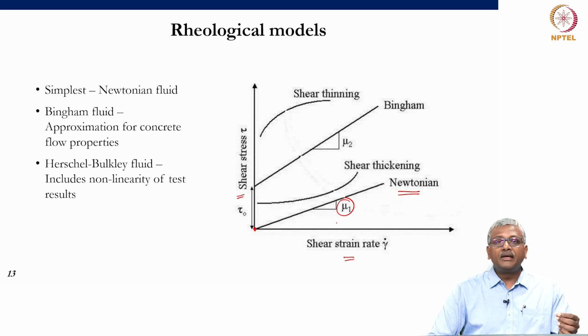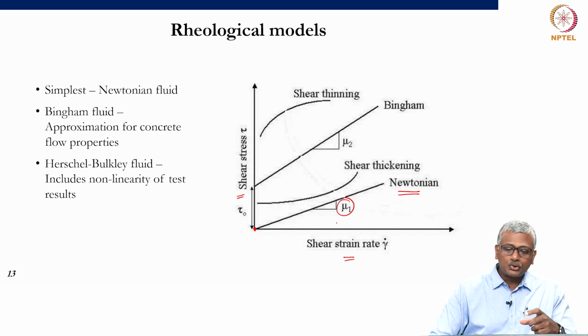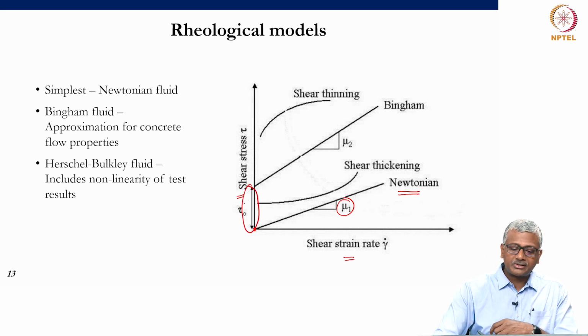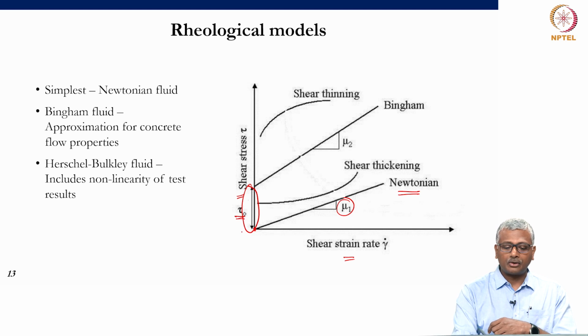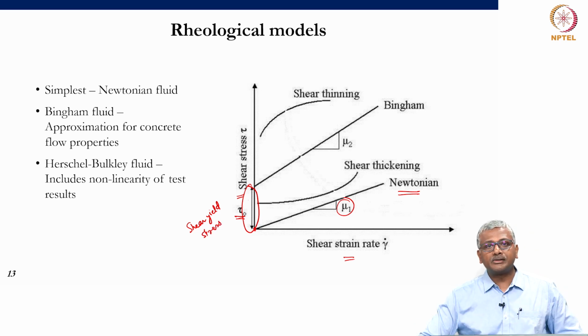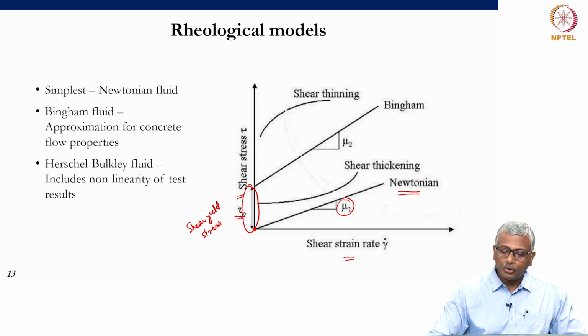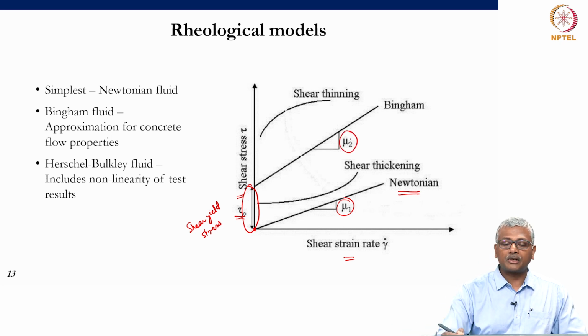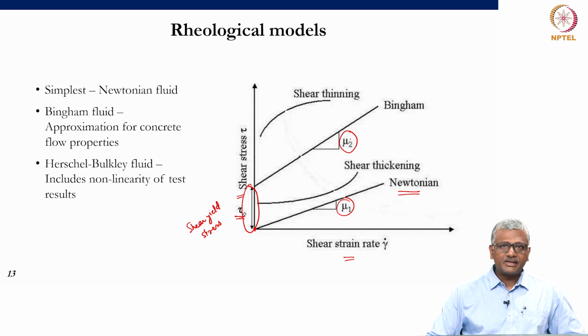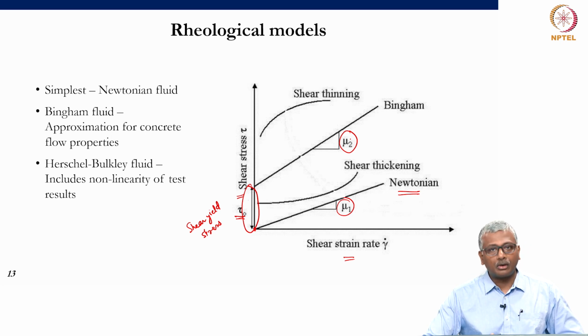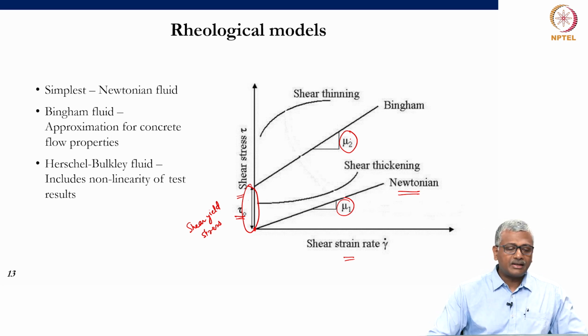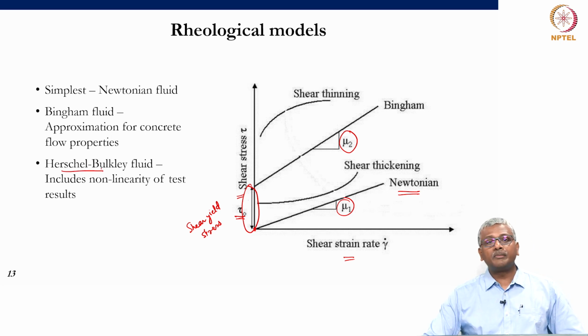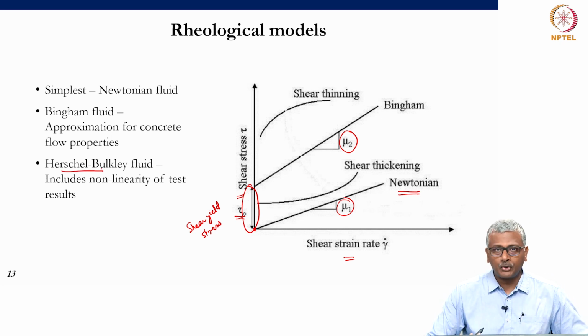Okay. Bingham fluid is a material that has to overcome some initial shear stress, which is represented here as tau naught or shear yield stress. Once you overcome that initial shear yield stress, you can then start the particles to flow. Okay. And once it flows in a Bingham model, the flow happens with a constant viscosity. But this need not always happen with systems which are suspended solids in a liquid medium like concrete. You can also get some non-linearity, and for such instances, the Herschel-Bulkley fluid model is often used for concrete.